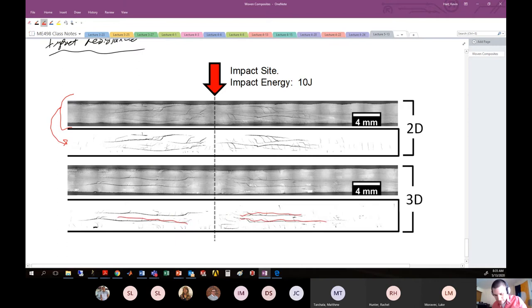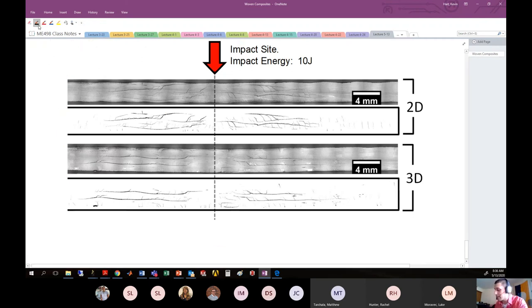All right, but generally what you can see is that the delaminations that form aren't as widely open. So if you, for instance, look at this guy, this guy's open a pretty good amount, right? So the opening there is very large compared to, let's say, the openings here, not as large. You can quantify this information and show that 3D composites generally have less internal damage from impact than 2D composites would. All right, so